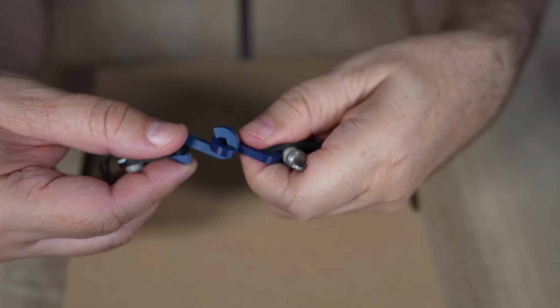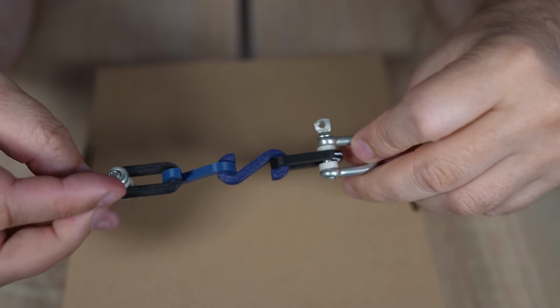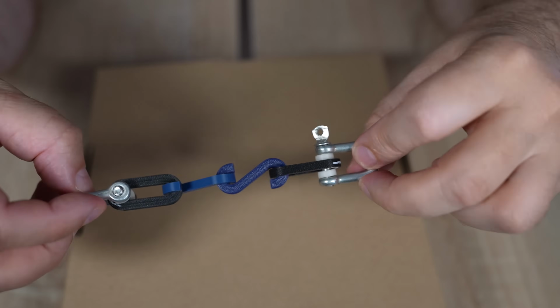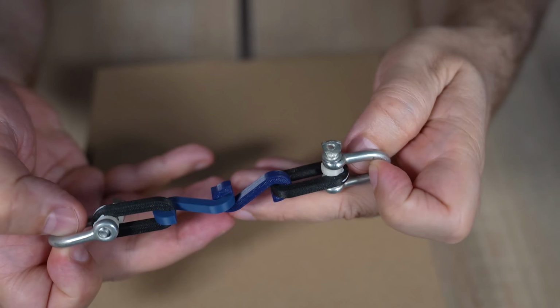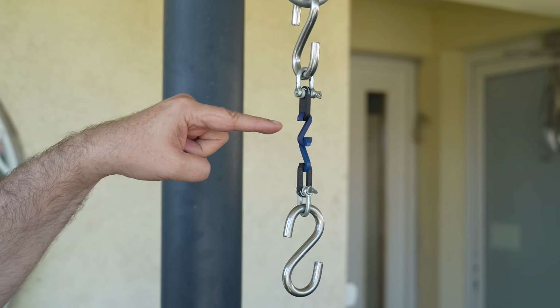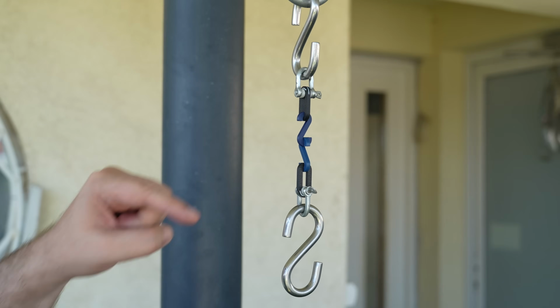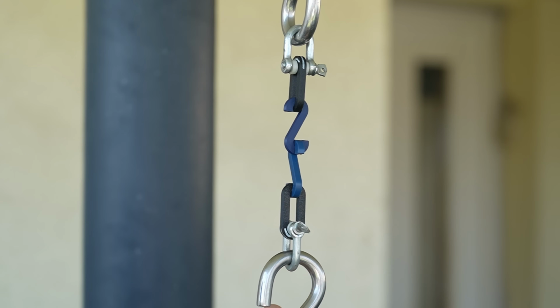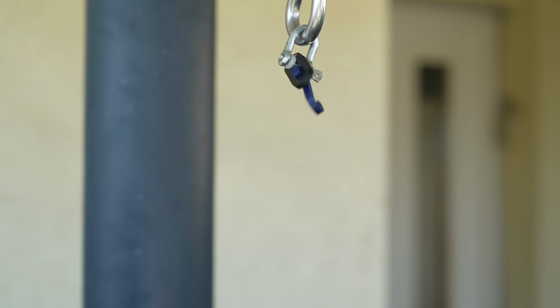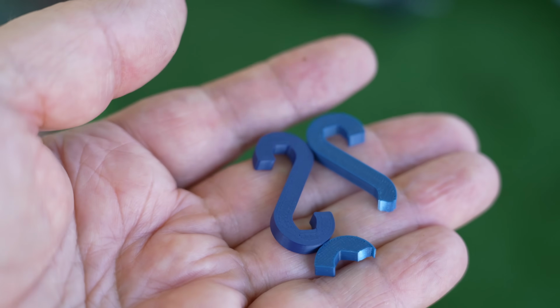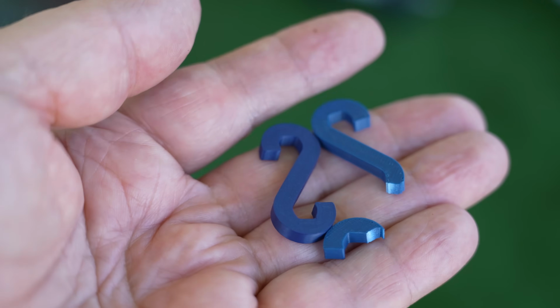And now the elimination hook test, when the weakest falls out, but of course in this case I have only 2, so it will be only one pulling. Prusament, Stratasys. This footage is slowed down 8 times, and we can clearly see the winner. And the winner is Prusament. Not really what I expected.